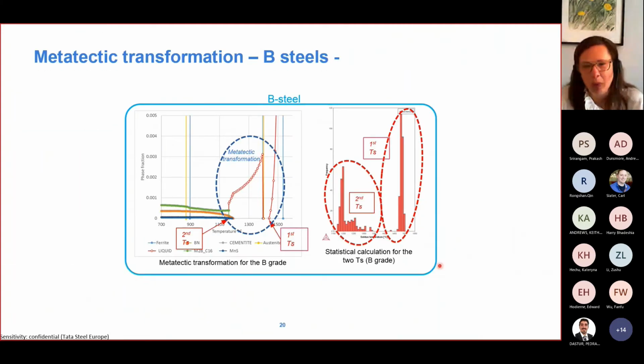The boron steels also have something very funny, a not very well known transformation called a metatectic transformation in a phase diagram. This transformation is exactly the opposite, like turning a peritectic transformation upside down. In a peritectic transformation, we go from two phases, a liquid and a solid phase, and transform to a third phase, which is also solid. In this case, it's the other way around. We go from one phase that is fully solid, and transform to two phases, one of which is liquid. So practically, everything has solidified, and suddenly you have liquid again.